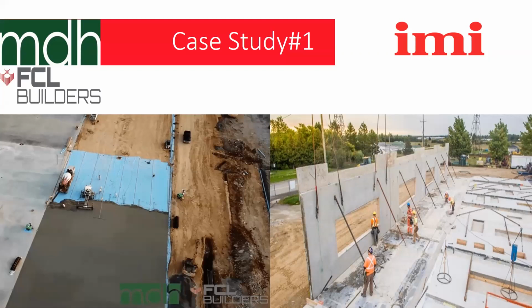So as you can see to the left, that's us pouring our slab on grade mix. We were able to optimize and use a blended aggregate mix, which, anytime you can get the most out of your aggregate, will lower your cement content, essentially lowering the carbon footprint. So we were able to do that for the slab on grade, and then also able to reduce around 10 to 15 pounds of cement per yard using the CarbonCure technology. So we had some really good results and feedback from that.